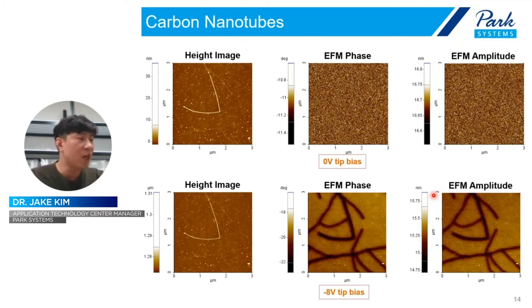Here is another one, the carbon nanotube. It's quite the same as the previous image. In the height image, there is no CNT. Oh yeah, it is very difficult to see the CNT, the carbon nanotube. And if we didn't apply the bias, there is no signal. But when we apply the tip bias, in this case -8 volts of tip bias, we can see quite an obvious carbon nanotube and obvious EFM signal.